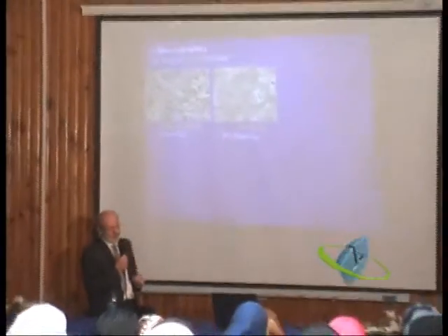And we have a range of these glass ceramics. In the past, we had these mica-based systems, the Dicor, which are no longer popular, but these were classic fluoride or mica-based systems. We had the leucite-based systems. We had the recent systems where people such as IPS Empress with Eris are putting both a calcium and a fluoride system, so we're getting a fluoroapatite structure in those systems.